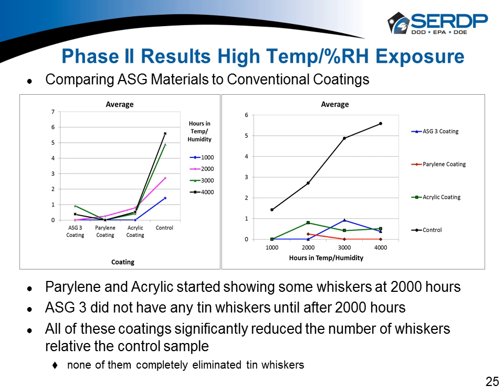If I jump out to slide 25, this is the data that compares how the liquid glass or the ASG coatings did against conventional, which was our Parylene and our acrylic. And sure enough, just like before, the initial 1,000, 2,000 hours, the acrylic and Parylene are looking real good, but in the last half of the test, from 2,000 hours up to 4,000 hours, as the whiskers continued to grow, and of course underneath there, the acrylic or the Parylene do not have the benefit of having nanoparticles or being able to seal off the surface. They just don't have the same material characteristics. We know that moisture vapor goes readily through acrylic, and it also goes through Parylene just at a slower rate. But that moisture, once it gets down to our tin surfaces, then starts to interact and lets the whiskers initiate. And by the time we get out to 4,000 hours, those coatings were worse than the control, and a couple of our ASG coatings were performing as good or better than the controls.